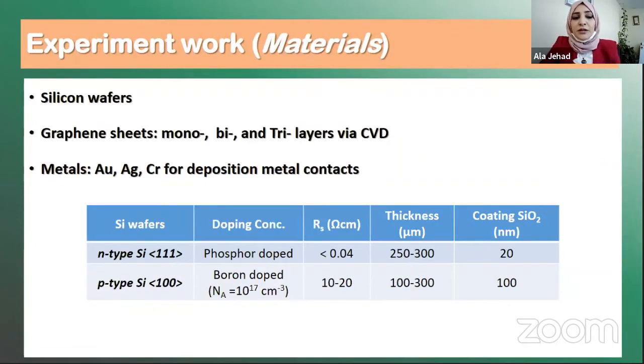In my experiment, I used two different types of silicon wafer, as you can see in the table. I used N-type silicon with orientation 111 and P-type silicon 100. We synthesized the graphene by CVD methods, producing monolayer, bilayer, and trilayers of graphene. We also need metals to make a contact for the cell, so we used chromium, gold, and silver.